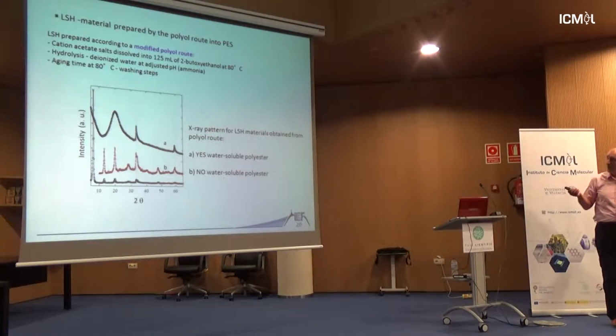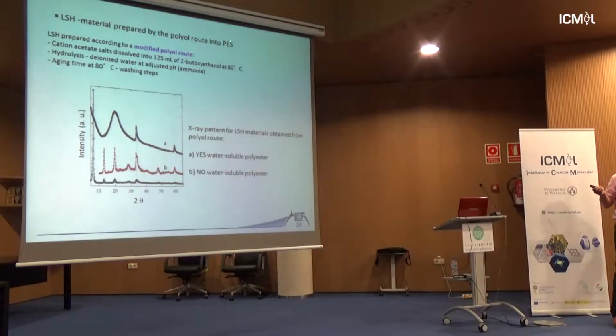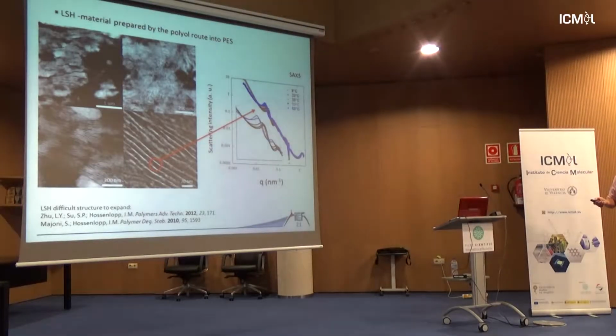So for the LSH, we have prepared LSH directly in the waterborne polymer, and you can see that we can get the LSH from single metal acetate, forming the LSH inside the polymer, and we have formed the 2D structure. There is no problem. And under TEM, we can see the layers of LSH, and it's even expandable. That's quite unusual, because it has been reported in the literature that layered single hydroxide is very prone to keep its basal spacing intact. It's very difficult to prop apart the LSH layer structure. So that's quite interesting.